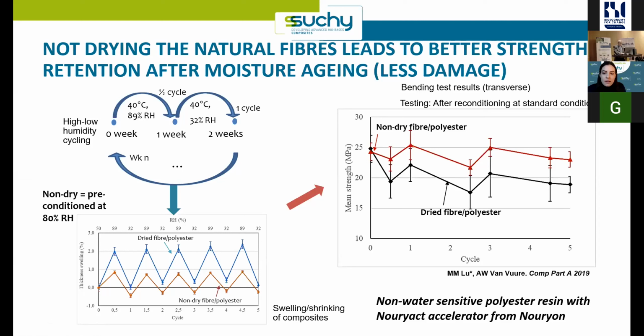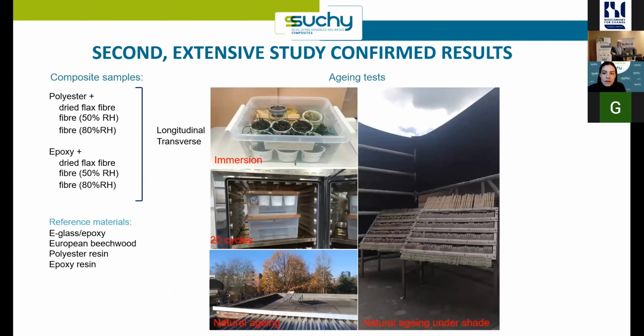So we did a big second study in Leuven on this whole idea of not drying the fibers and looking at various aspects. So we went not just to polyester, but we also used epoxy. We had fully dry, 50% preconditioned, 80% preconditioned. We benchmarked it with e-glass epoxy, wood, and just the pure resins. And then we did 4 different protocols, so a very extensive study, which is part of the PhD of Marissa Lou, who is now graduating in March. So congratulations to Marissa for this nice work.